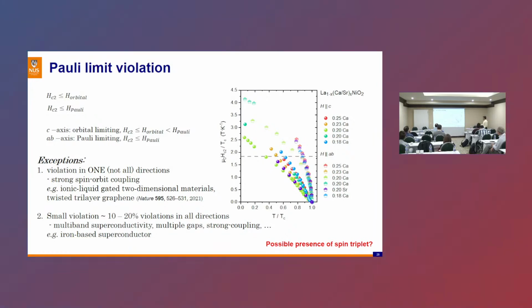So you can have a violation, for example, in one of the directions, which has been shown in the case of tri-layer graphene, right? And this can be nicely explained by spin-orbit coupling locking your Cooper pair in, for example, the plane, okay? There are also small violations that are sometimes observed in, for example, multi-band iron-based superconductors, but it has never been seen to be like 3 times the Pauli limit, okay? So this is something that we are really struggling to understand, and we are trying to do more experiments right now to pinpoint the reasons for these violations of the Pauli limit of the critical field.